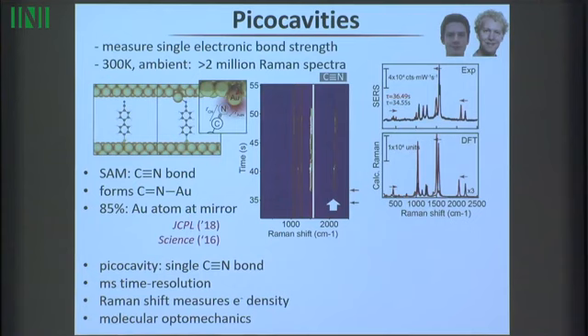And the way, if I try and solve electromagnetism now, I have a problem because I'm trying to do it around a single atom, and I shouldn't be able to use classical mechanics for that. So we've used these very tiny 1 nanometer chunks with the full quantum theory to show that, okay, the hand waving is not so bad. When I solve it, this is actually acting as a lightning rod on the single atom scale. So it concentrates a field. A lightning rod will actually concentrate any electrical field into it because it's very sharp. And this is now working at optical frequencies on the single atom scale, and it concentrates the light still further, and it concentrates it near this bond.